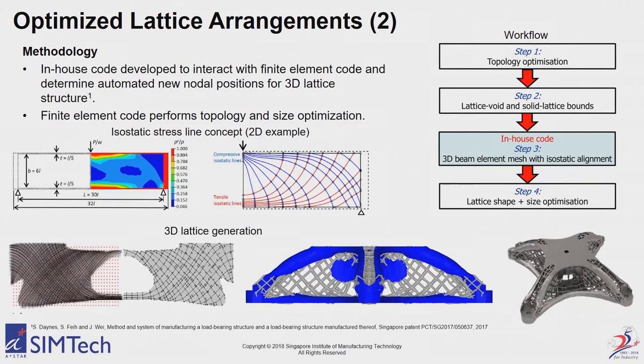So all the nodes get placed in the optimum locations within a varying box movement, and we're also optimizing the diameters. The one thing we see here is that the diameters actually stay a lot more uniform than with the other processes. One can imagine that if we can play with the size and orientation of the cell, the diameter variations have to be a lot less to lead us to an optimal stress state. And as I said, we can do this in full 3D now.